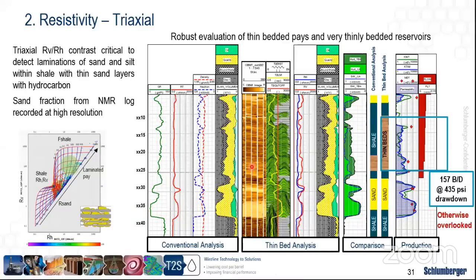But when we looked at the wellbore image, there were actually thin laminations detected by the image, as well as the NMR, nuclear magnetic resonance. When we resolved RV and RH, you can see that initially, if we were just dependent on the RT itself, we would see a very low resistivity response that would be misleading for formation evaluation. But when we resolve RV and RH, we can start to see that the vertical resistivity is a bit higher compared to what we see in the RT.